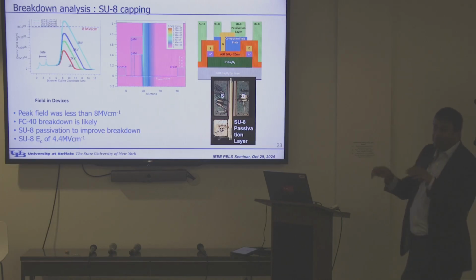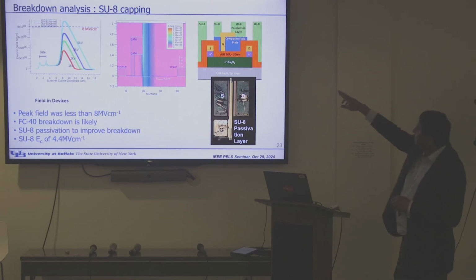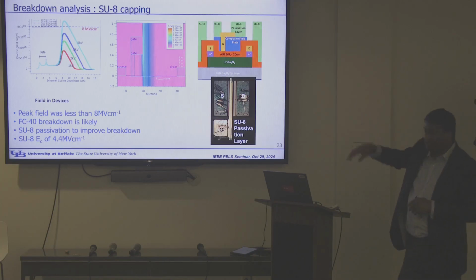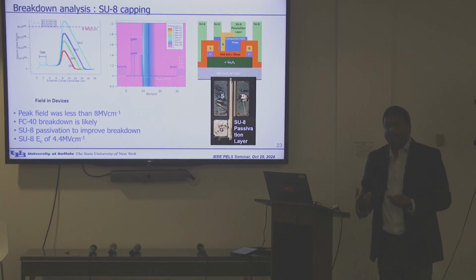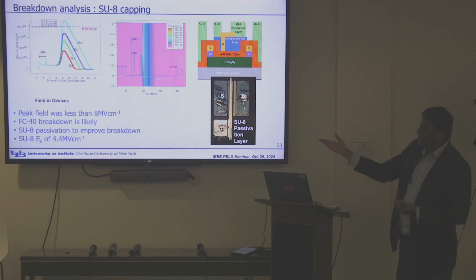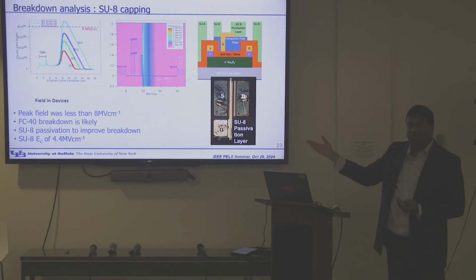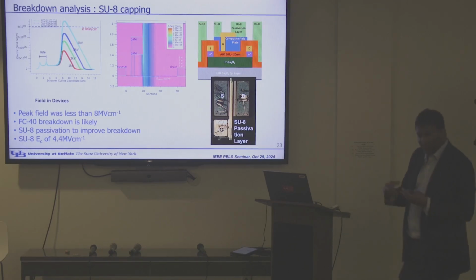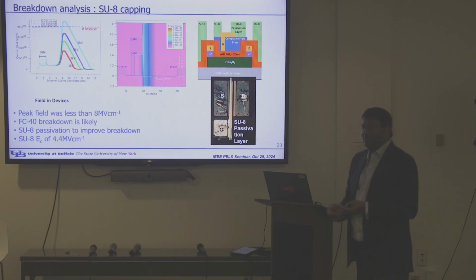You just cap it with some high field strength material. You can see here, you use SU8, which is actually photoresist, right? It's actually 4.4 megavolt per centimeter, which is higher than silicon carbide or gallium nitride field strength, right? It's surprising that it's just a polymer. But isn't it kind of defects, lots of defects in SU8, or is it?